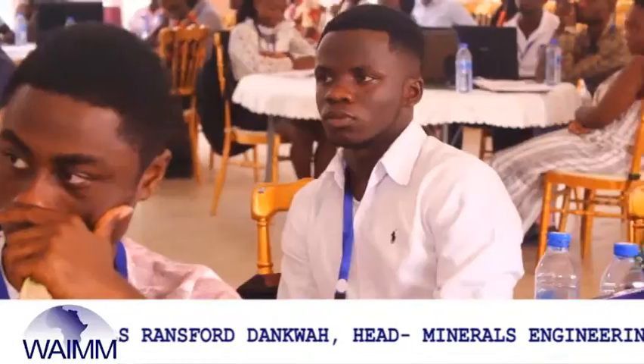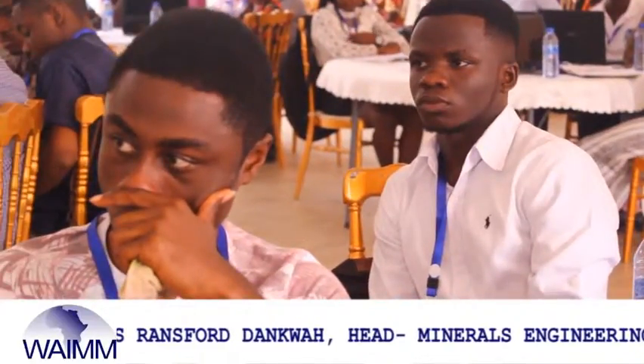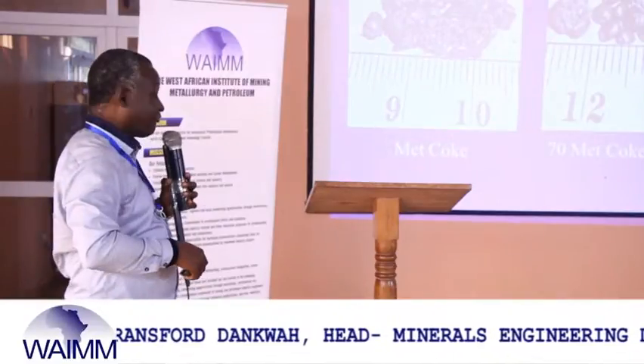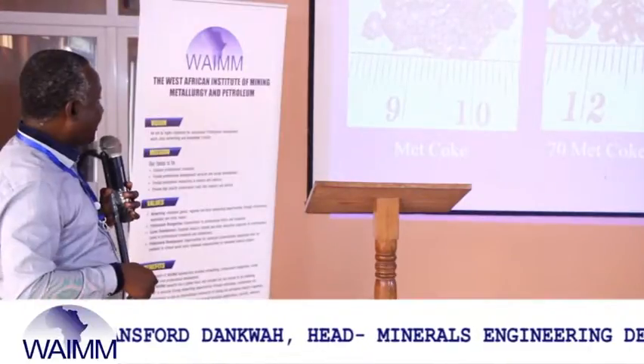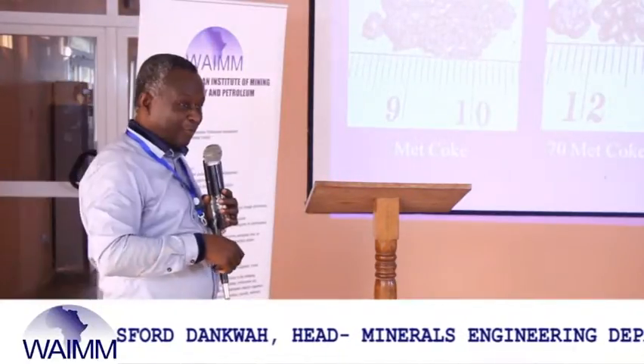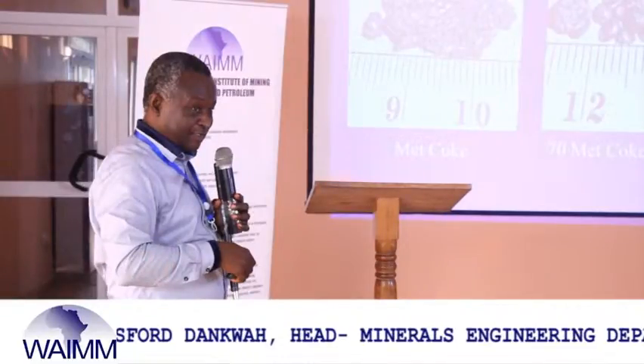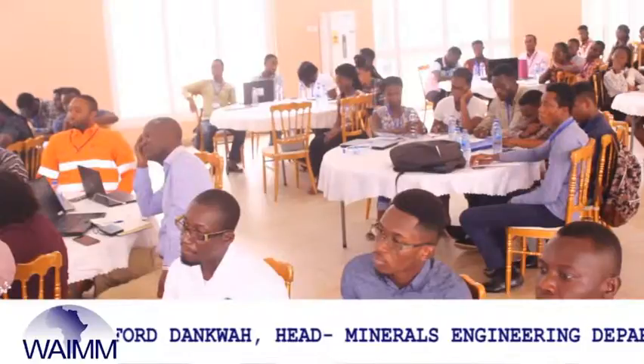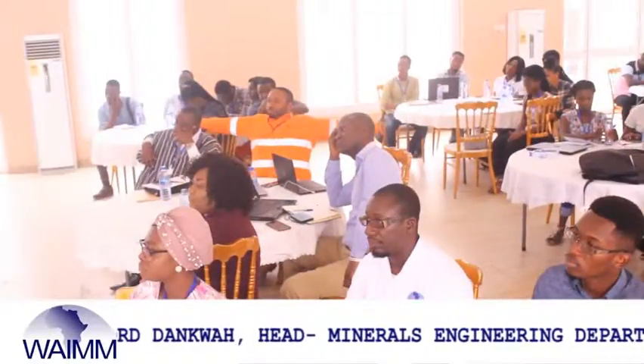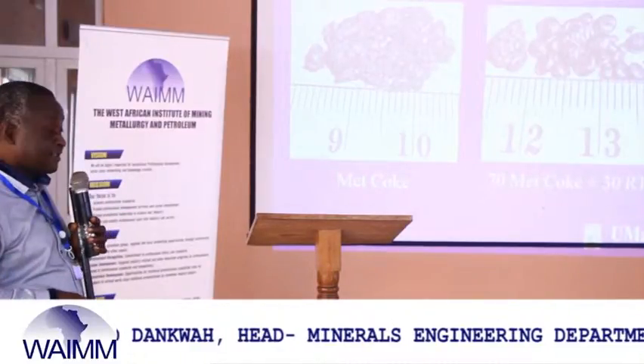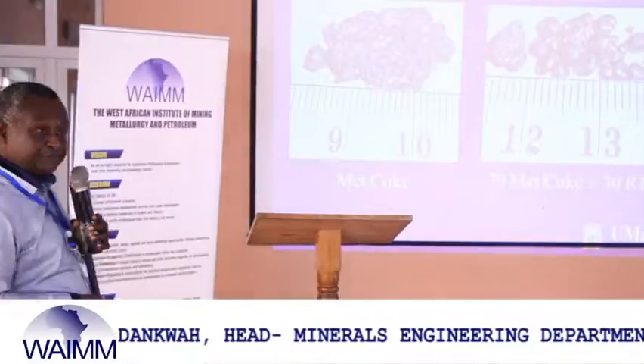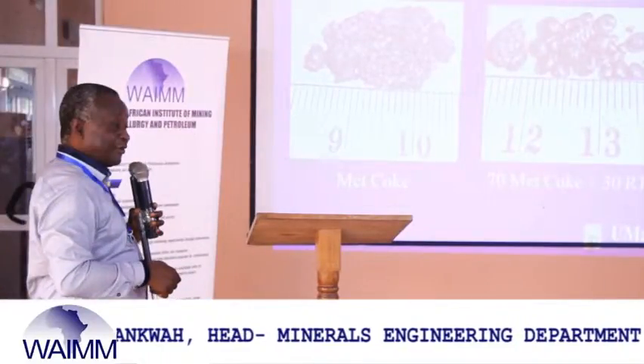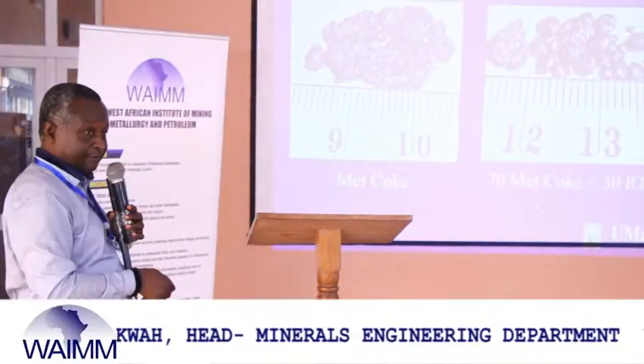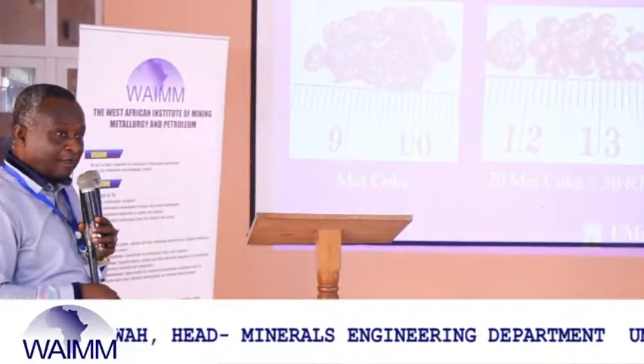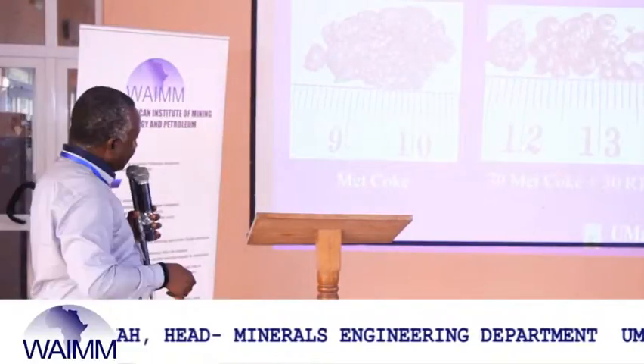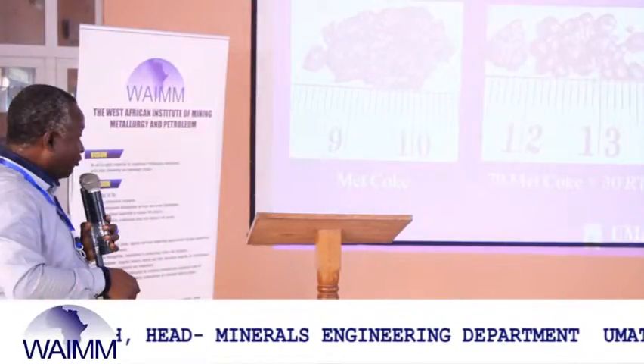Now look at this. This is iron that was produced using 100% metallurgical coke from the industry. If you look at it critically, you will see that separation of the metal from the slag and other unwanted debris was difficult. We then took 30% of the metallurgical coke away and added just 30% rubber tire. If you compare these two separations, you notice that as you introduce the rubber tire, you are able to separate the metal from the unwanted material. So right away, we knew that we were moving towards achieving something better than what was existing in industry.